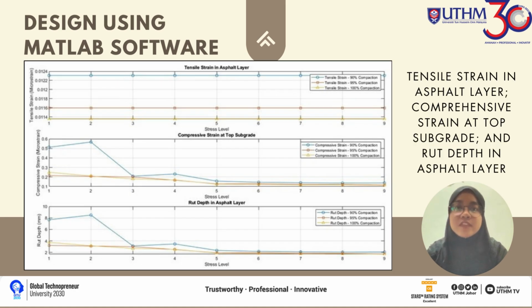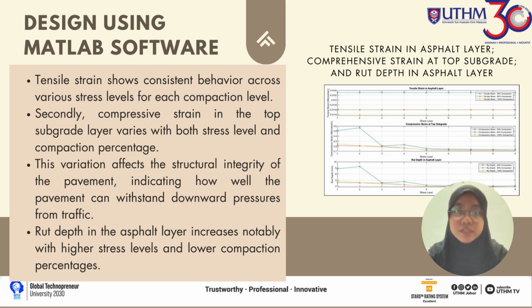Next, we have tensile strain in asphalt layer, compressive strain at the top subgrade, and rut depth in asphalt layer. Firstly, tensile strain, which measures how materials stretch under load, shows consistent behavior across various stress levels for each compaction level. The consistency highlights the predictable relationship between applied load and the material stiffness. Secondly, compressive strain in the top subgrade layer varies with both stress level and compaction percentage. The variation affects the structural integrity of the pavement, indicating how well the pavement can withstand downward pressure from the traffic. Lastly, rut depth in asphalt layer increased notably with higher stress level and lower compaction percentage.